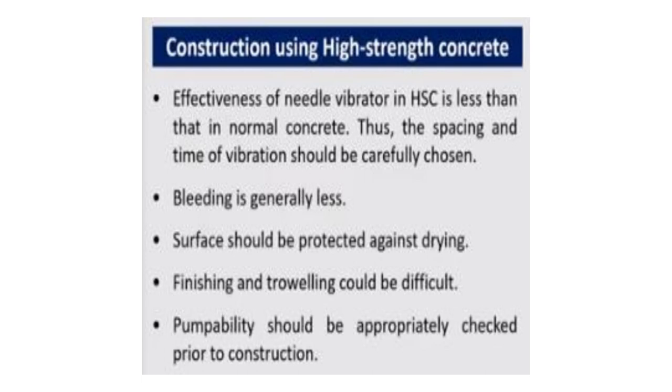The effectiveness of a needle vibrator in HSC is less than that in normal concrete, thus the spacing and time of vibration should be carefully chosen. Because it has a lower water cement ratio, the effectiveness of the needle vibrator in HSC is a little lower as compared to normal concrete. Therefore, the spacing and time of vibration should be carefully chosen, otherwise there is a chance of segregation.